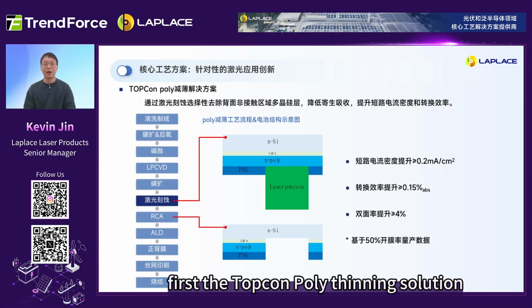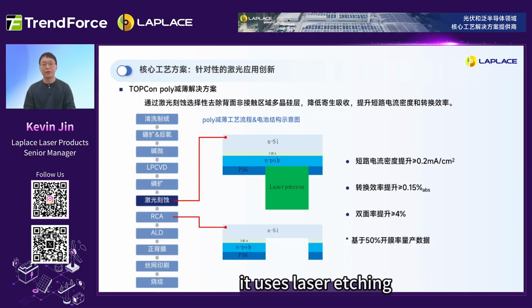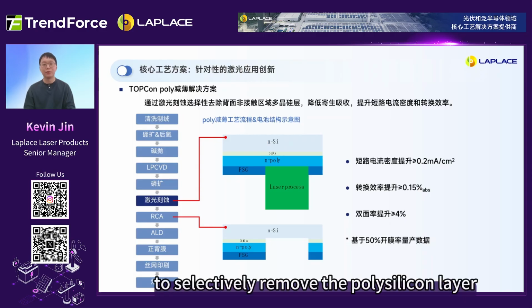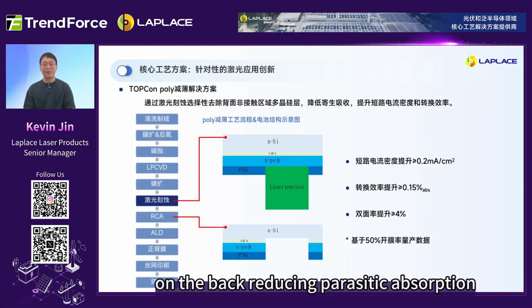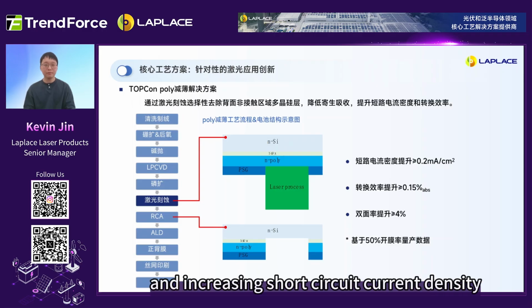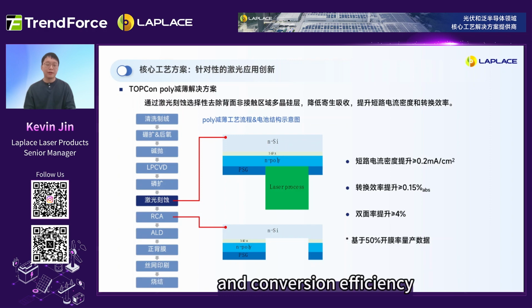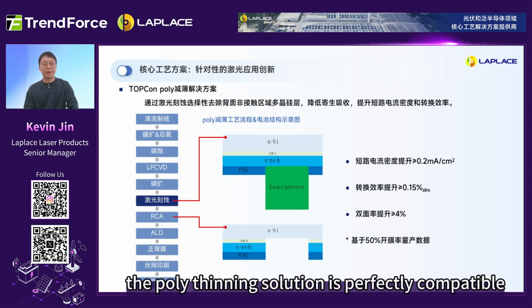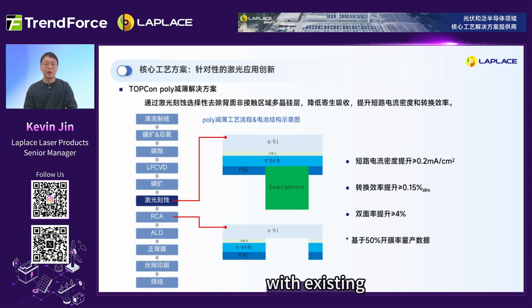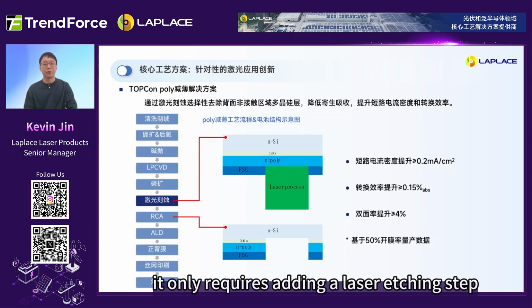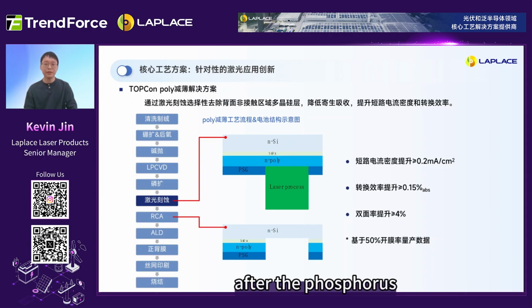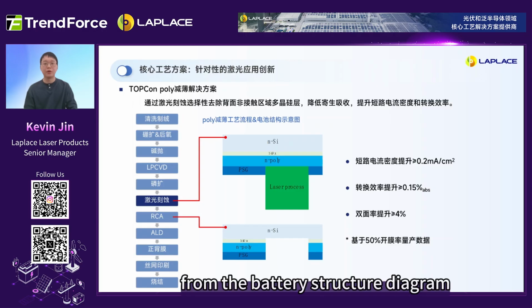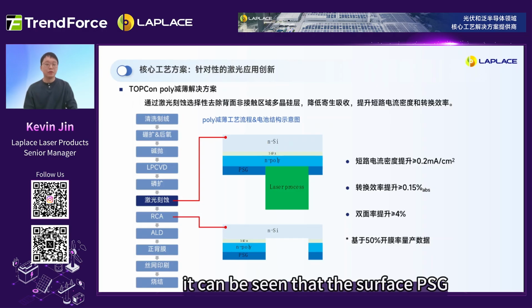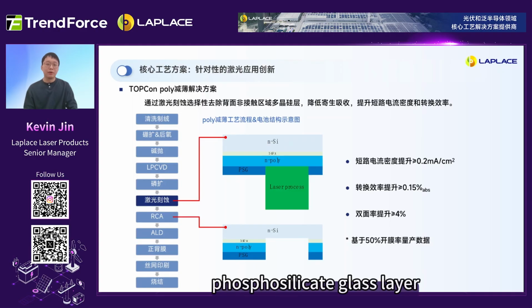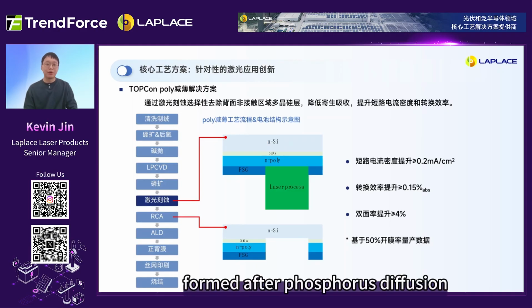First, the TOPCon polythinning solution. It uses laser etching to selectively remove the polysilicon layer in non-contact areas on the back, reducing parasitic absorption and increasing short-circuit current density and conversion efficiency. The polythinning solution is perfectly compatible with existing TOPCon process flows. It only requires adding a laser etching step after the phosphorus diffusion process. From the battery structure diagram, it can be seen that the surface PSG, phosphosilicate glass layer formed after phosphorus diffusion is used as the laser absorption layer.